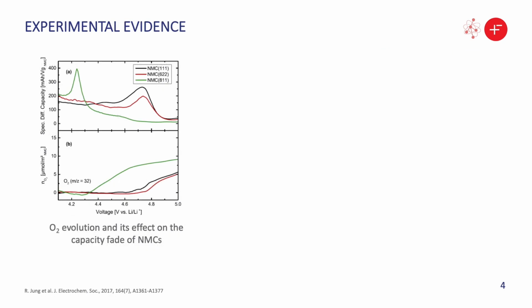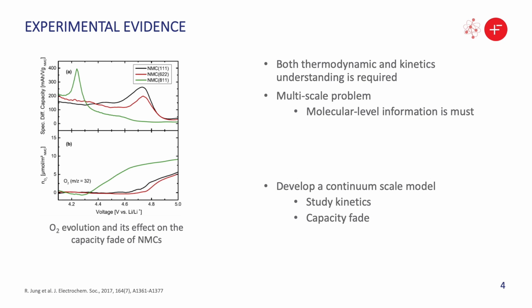As mentioned in the previous slides, here comes the experimental evidence that there is a decay in the specific capacity of NMC electrodes, and it is related to the increase in oxygen release, or the evolution of oxygen, whenever these electrodes are cycled at around 4 volts or higher. To understand or model this phenomenon, both thermodynamic and kinetic understanding is required, and it is also a multiscale problem. So a lot of molecular-level information is a must to model this phenomenon. At the same time, we need to develop a continuum-scale model to study the kinetics and see how much capacity fade is happening because of this phenomenon.